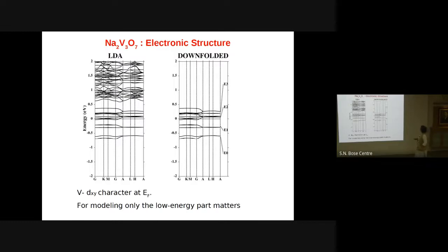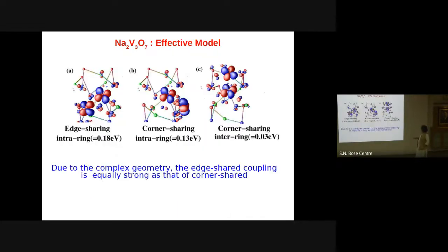So if you do a LDA DFT calculation of this compound, this is basically the so-called band structure, and we are interested only in the bands that are close to the Fermi level, and these are the bands which are basically arising out of the vanadium dxy orbitals. And through downfolding, what we did, we basically picked up only these bands. And there are actually 9 bands, you can count that. And then what we find, we constructed this Wannier function, we find that there are interactions within the ring and between the rings.